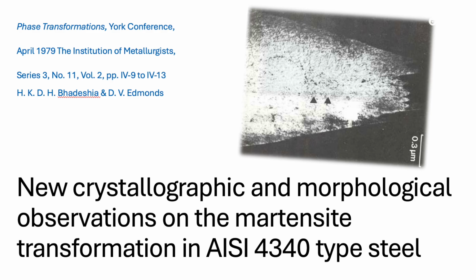It boils down to strain energy. The martensitic transformation involves a huge rearrangement of atoms, a significant shape change at the atomic level. Right, it's like trying to fit a slightly different shaped block into a hole. Creates stress. A lot of stress. Internal stress, what we call elastic strain energy. Now, if the transformation happens lath by individual lath, each one creates its own intense, localized stress field.